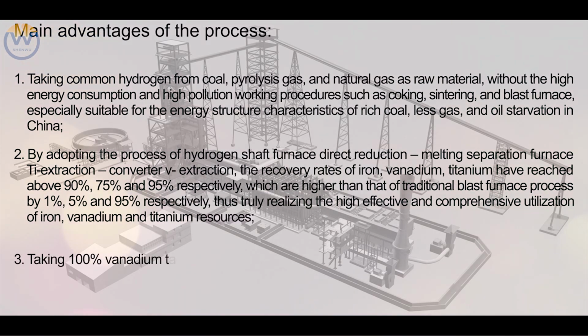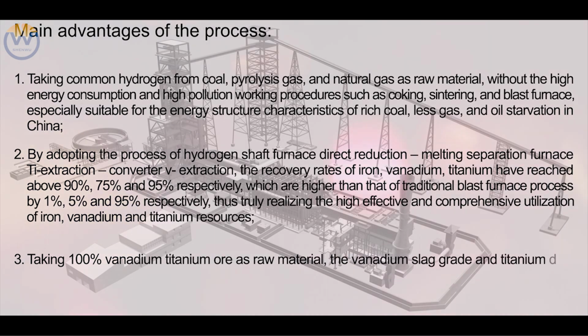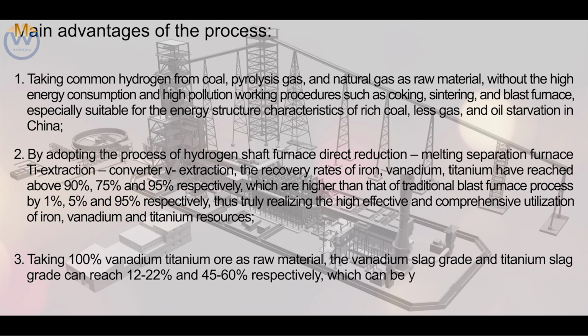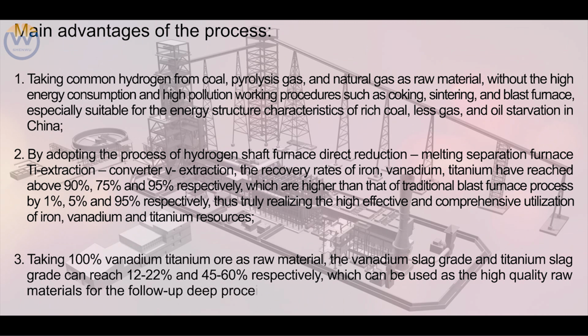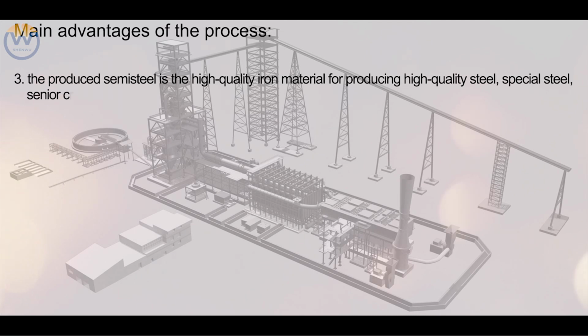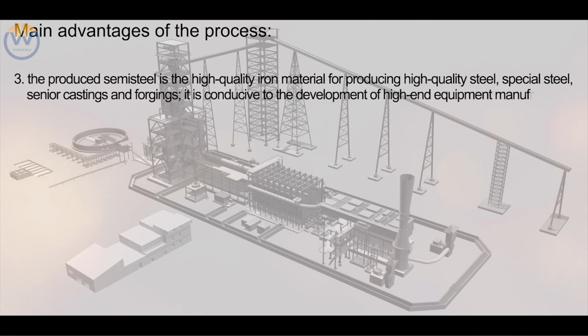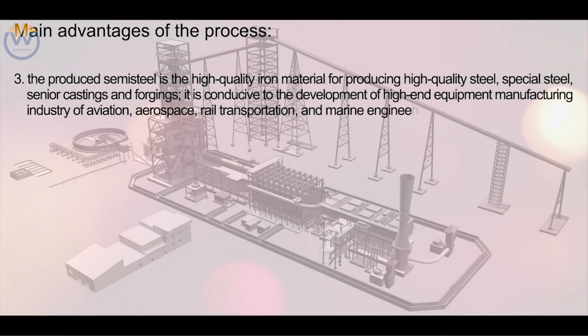3. Taking 100% vanadium titanium ore as raw material, the vanadium slag grade and titanium slag grade can reach 12 to 22% and 45 to 60% respectively, which can be used as high-quality raw materials for the follow-up deep processing of vanadium and titanium. The produced semi-steel is a high-quality iron material for producing high-quality steel, special steel, senior castings, and forgings. It is conducive to the development of the high-end equipment manufacturing industry of aviation, aerospace, rail transportation, and marine engineering of China.